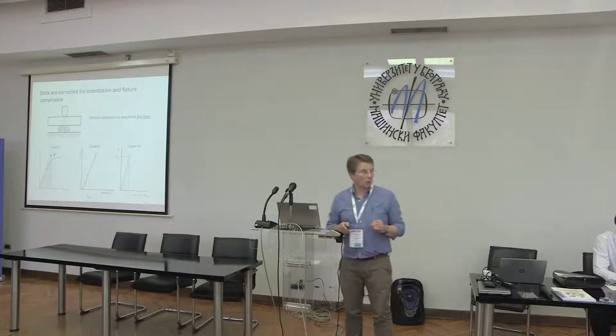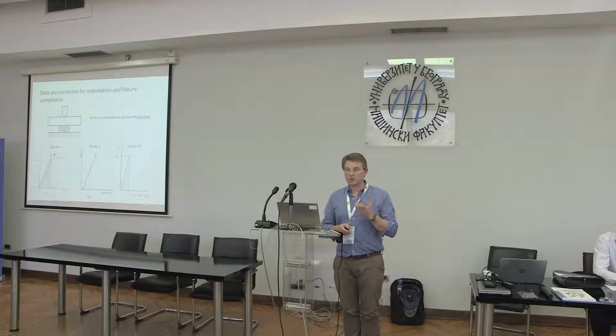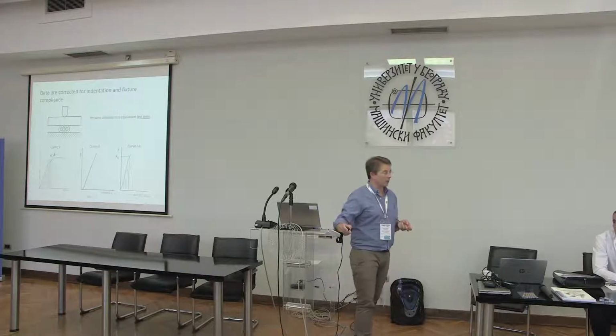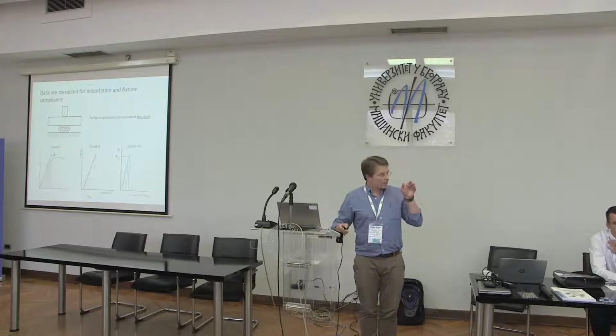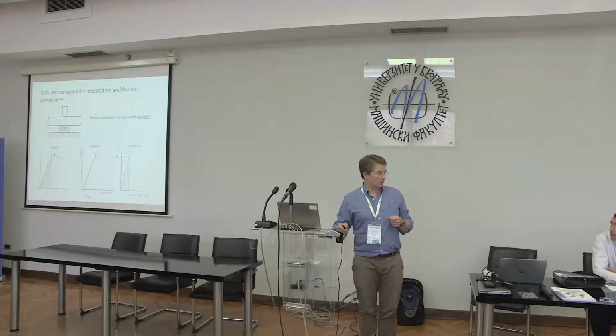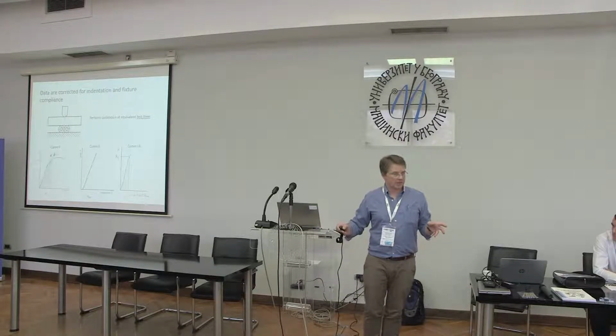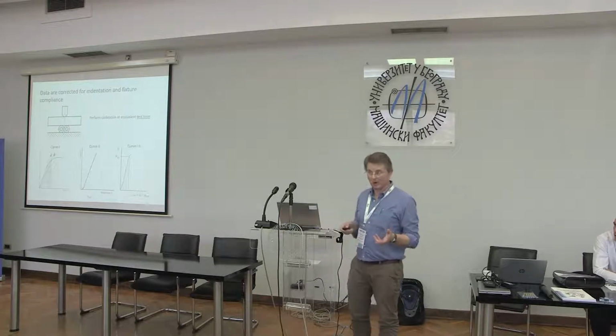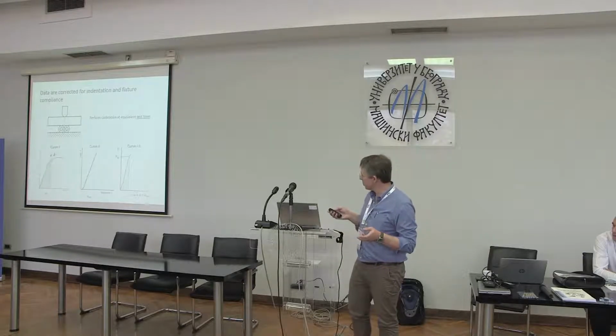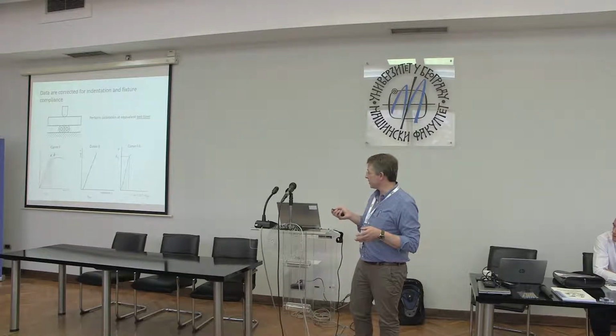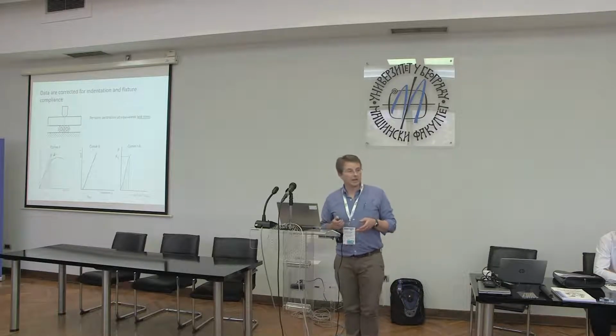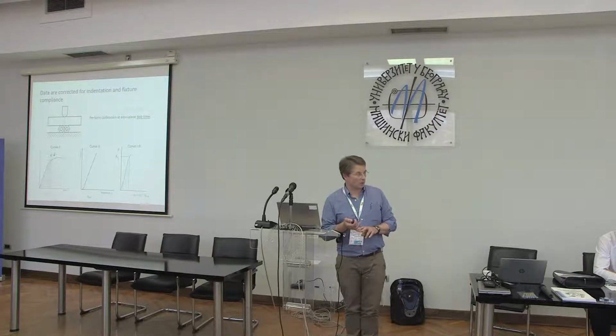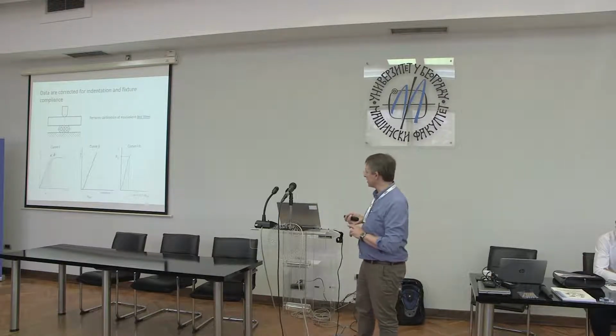A complexity with polymers, of course, is that they are generally much softer than a metal. So we have to worry more about indentation. When we're loading these, for example, on the 3-point bend rig, the indenters may indent quite significantly into the polymer material. So we have to correct for that indentation, and of course we always have to correct for any compliance effects in the test machine. So we have a simple routine built into the standard which basically says that you perform a calibration with, for example, the loading rollers pushed together, so no crack involved, and all you're measuring here is the indentation of the loading rollers into the specimen and the specimen compliance.